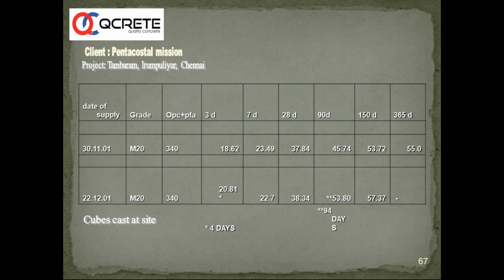So what we are talking about here is there is a significant jump between 28 days later on, and of course this depends upon the fineness of fly ash and the reactivity of fly ash. Also it depends upon the type of cement and fineness of cement and several other properties of the combination. But one can be assured of the fact that whenever we are using OPC plus fly ash mixes, you are getting a very good strength at the end, especially after 28 days.